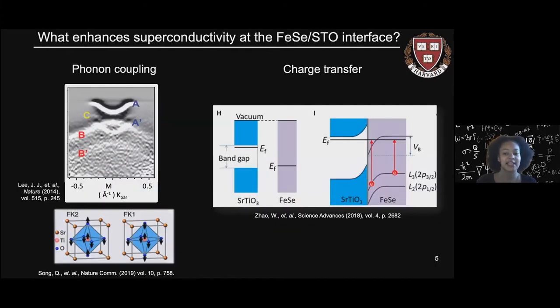Some previous studies have proposed two prevalent mechanisms for interfacial superconductivity enhancement. The first is phonon coupling. So here is the electronic band structure of iron selenide on strontium titanate, where the researchers locate a main band A and a replica band A prime, indicating electron-phonon coupling is present. Here they show the most prominent phonon modes, FK1 and FK2, which are the surface phonons believed to couple to the electrons in iron selenide.